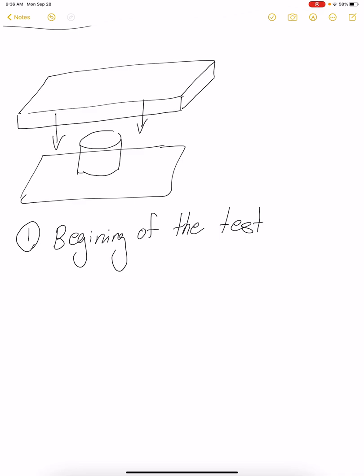But how do we know when the test has begun? We need to put a criterion. The criterion that we are going to use is a force criterion. Whenever our machine senses 25 pounds, that means that the surface has been touched. That's our surface detection criteria. 25 pounds seems to work well for our steel and aluminum specimens.